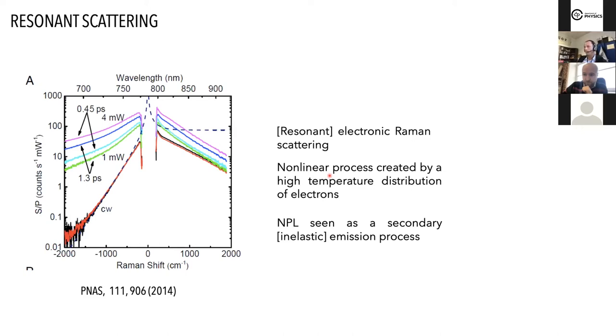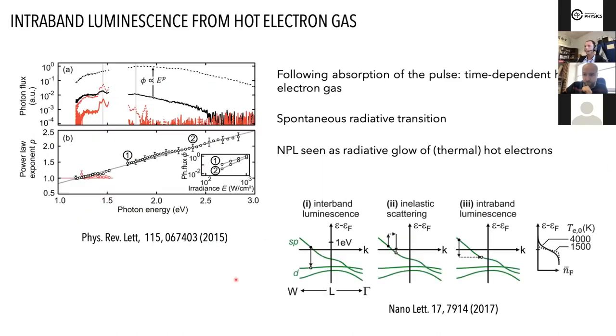And there is this beautiful paper from one year after, from the Lupton group, that actually revisited this interpretation from a slightly different point of view. But at the end of the day, the message is the same: after the absorption of the pulse by the nanoparticles, you have a time-dependent hot electron gas that will evolve eventually. And during the time where the electron system is really hot, it is able to emit a radiation spontaneously, through a spontaneous decay of this hot electron gas. And that lasts only for the time it takes to cool the electrons into the phonons.